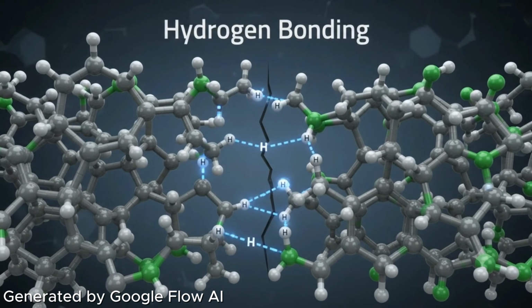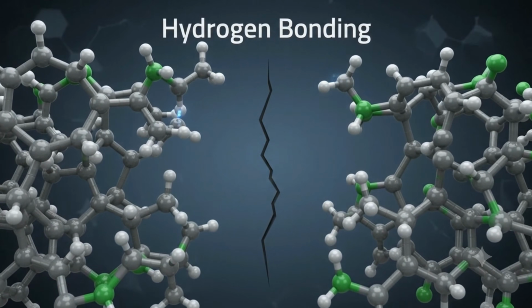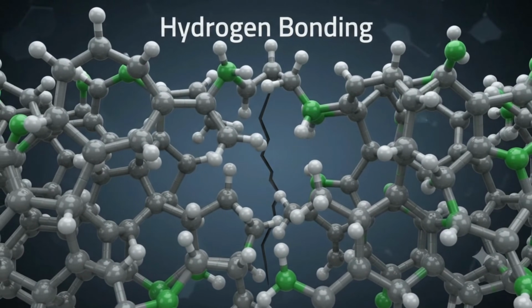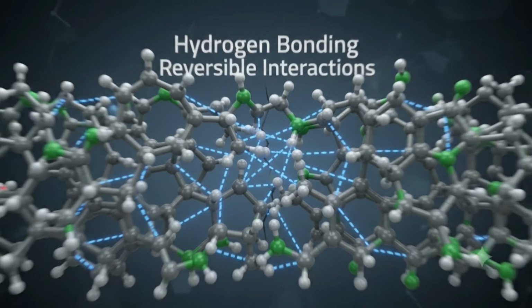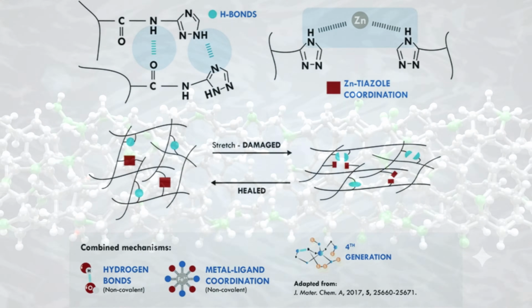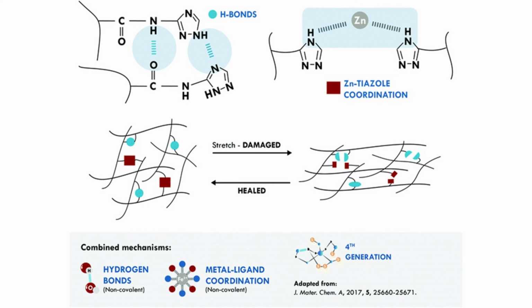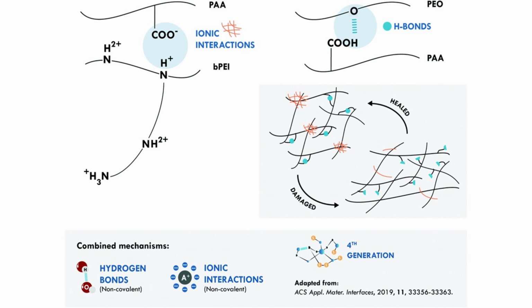Hydrogen bonding is one of the most widely studied mechanisms. Hydrogen bonds can dissociate under stress and rapidly reform once the damaged surfaces are brought together. In 2017, researchers showed that combining hydrogen bonds with metal-ligand coordination could significantly enhance self-healing performance. The combination improved both mechanical strength and healing efficiency, resulting in highly durable self-healing material. Two years later, hydrogen bonds were combined with ionic interaction. Working together, these interactions form strong yet reversible connections that enhance both strength and healing performance.